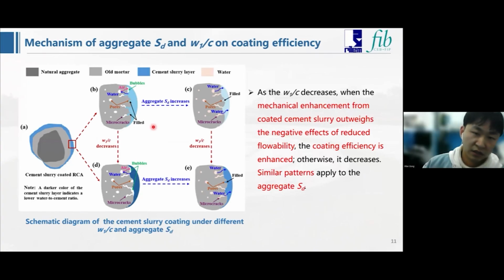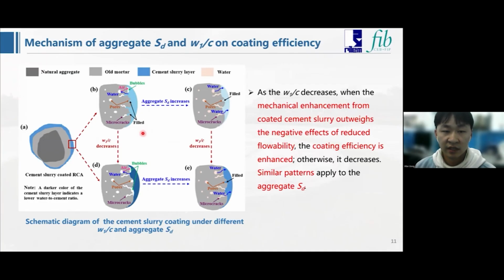So we can know the coating efficiency is influenced by both the mechanical properties and the flowability of the cement slurry. As the water-cement ratio decreases, when the mechanical enhancement from the coated cement slurry outweighs the negative effects of reduced flowability, the coating efficiency is enhanced. Otherwise, it decreases. Similar patterns apply to the aggregate SD.